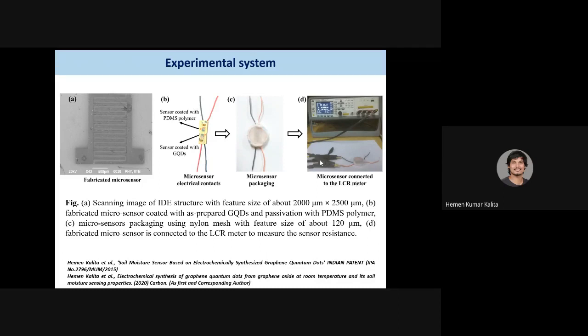So if you start from the initial step, we have graphene. From the graphene we have graphene oxide, which is the oxidized version. With the graphene oxide, we have fabricated another derivative of graphene, known as the graphene quantum dot, whose size is very small, around 3 nanometer. We fabricated it by a method known as electrochemical. And then we also fabricated a sensor with ID structure, and on top of the ID structure we deposited this GQD.